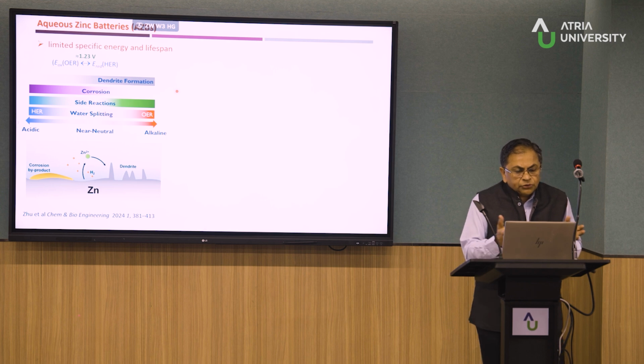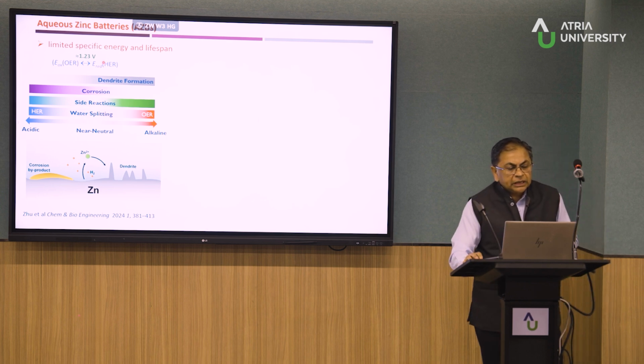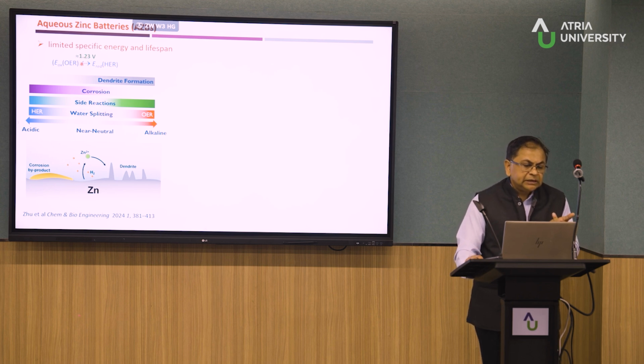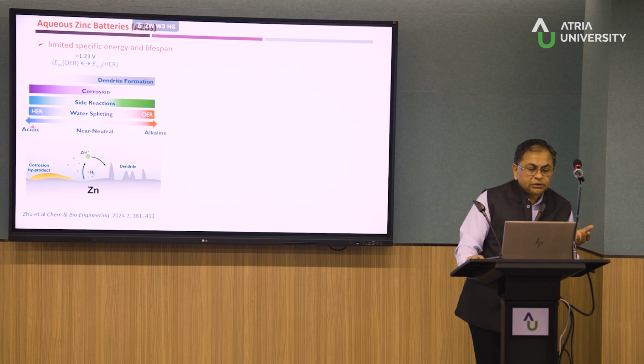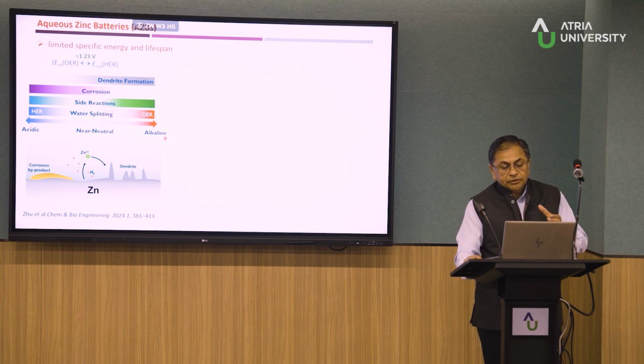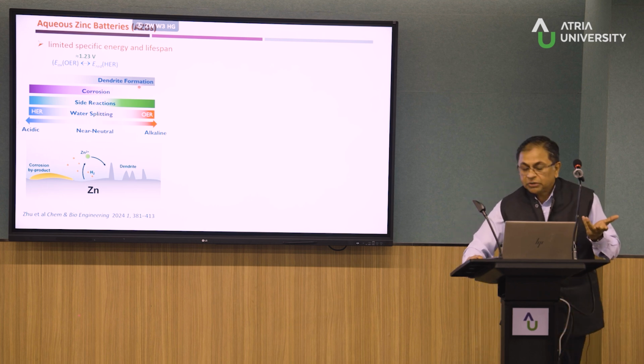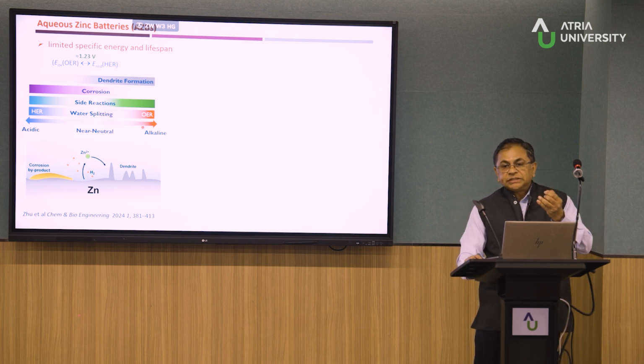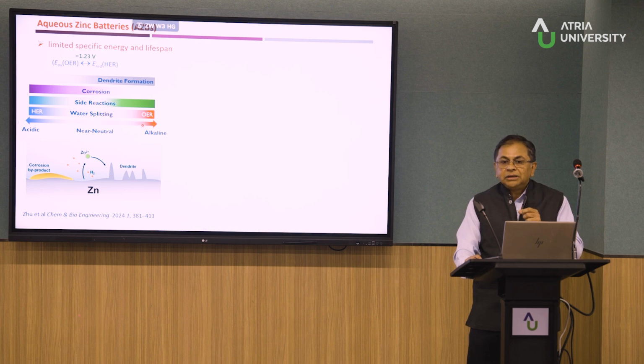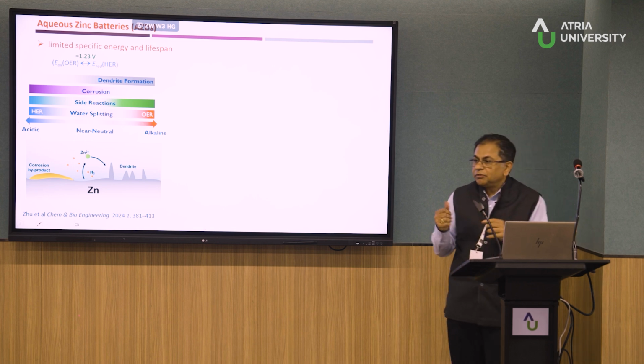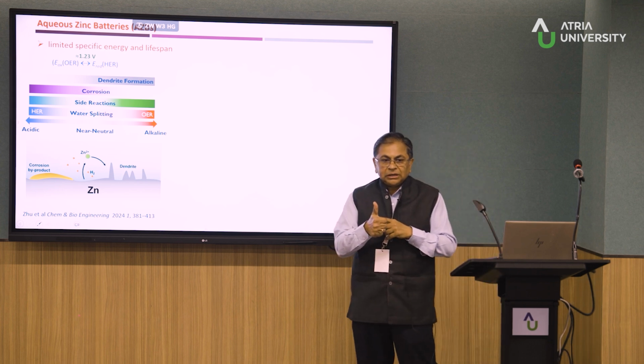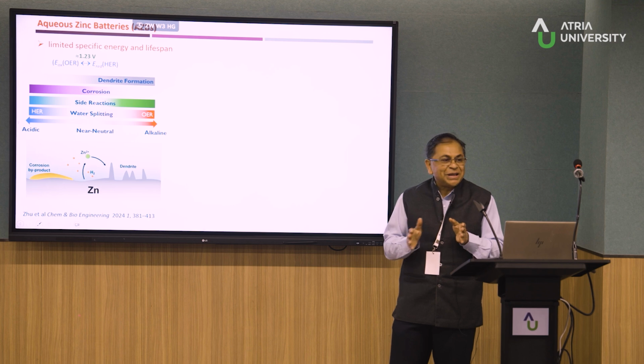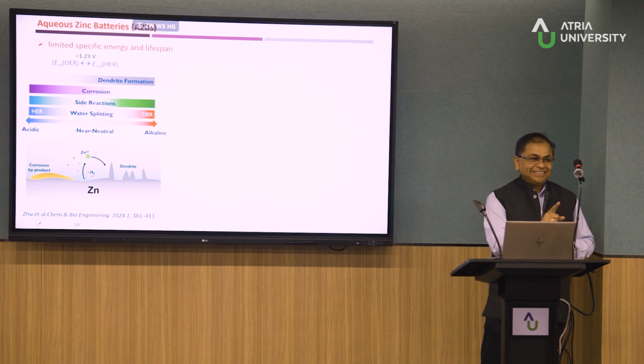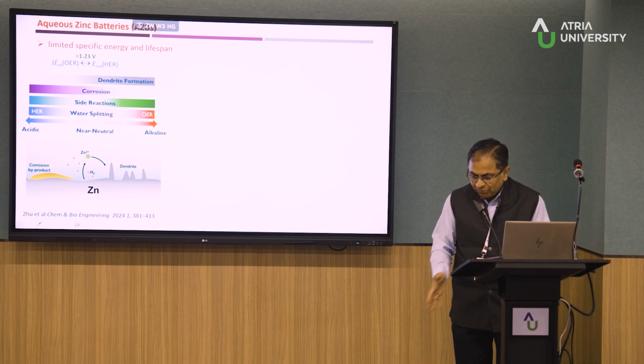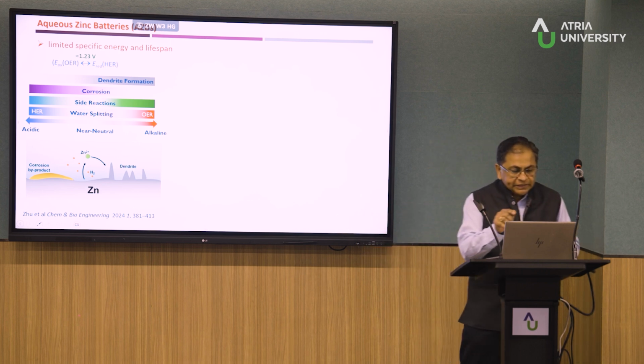But what are these associated problems? The problems are because this is pure water. We tend to work on the acidic or the alkaline end, just to increase the voltage range. But then you end up with a whole host of other problems like water splitting, side reactions, corrosion, dendrite formation. And the fun part is we have chosen zinc, but zinc is one which, in a non-aqueous system, if you have a new cathode, lithium cathode or a sodium cathode, you can quickly check against sodium. In an aqueous system, it is impossible, except zinc. It is troublesome, but if you put calcium or aluminum directly in water, you are done. Your battery is over. But zinc gives you that kind of an advantage.